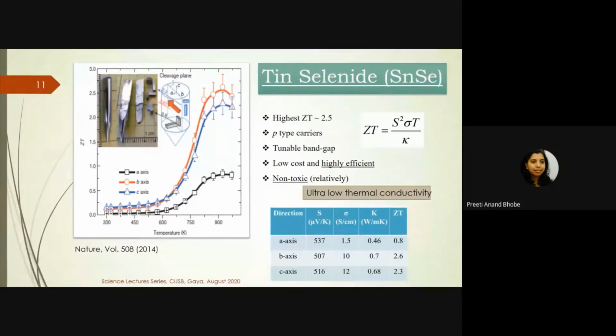Other than this property, what was interesting about tin selenide was that it was relatively non-toxic because it did not have elements like lead or tellurium in it, the ones which were there in bismuth telluride systems and lead-doped materials. Also, tin and selenium being less costly, they were low-cost, high-efficiency materials. These were P-type materials. It was found that this semiconductor is a P-type semiconductor, and it had a nice tunable energy band gap. Okay, so all these properties were very fascinating for having this material as a thermoelectric.